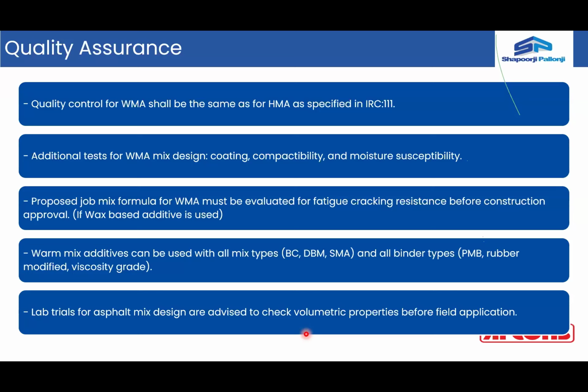What I feel is in SMA, you normally use the cellulose fibers also, and those cellulose fibers are addressing your drain down test because of the higher content of the binder. But if you go for a warm mix asphalt in SMA, you don't need to add the cellulose fibers because of the reduced temperature. The possibility of the drain down will be less in case of SMA if you are going for a warm mix instead of hot mix. And you can always check these things with the lab trials when you conduct the asphalt mix design, and check the volumetric properties before the field applications.